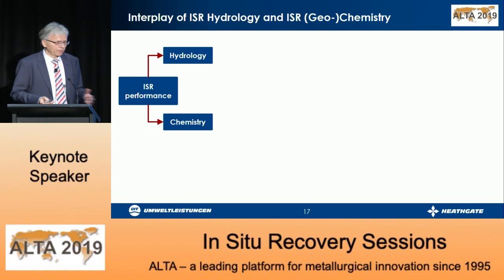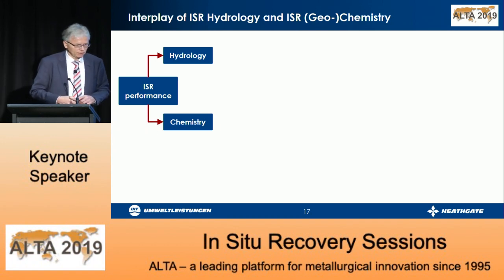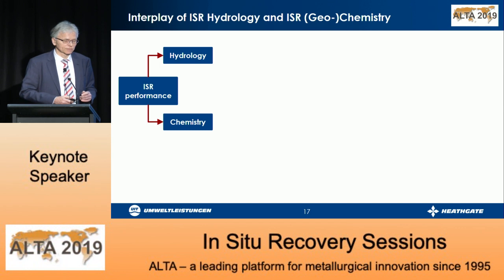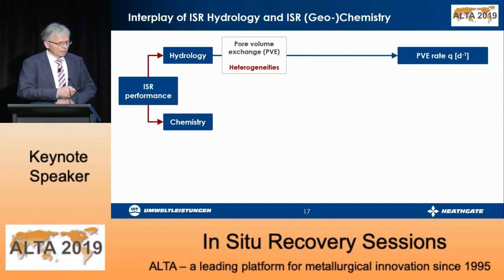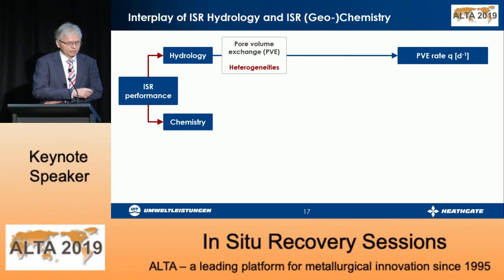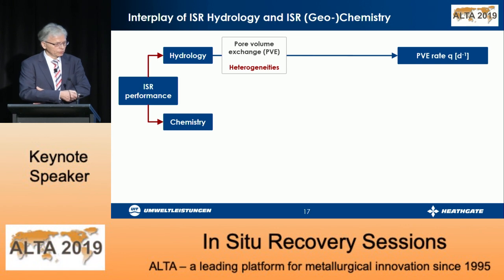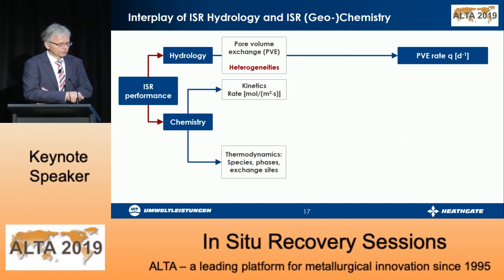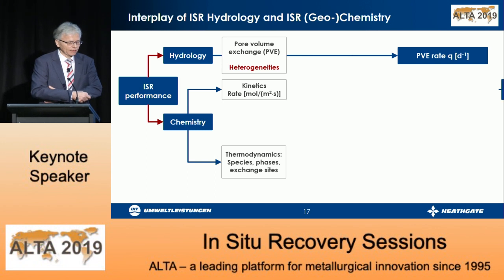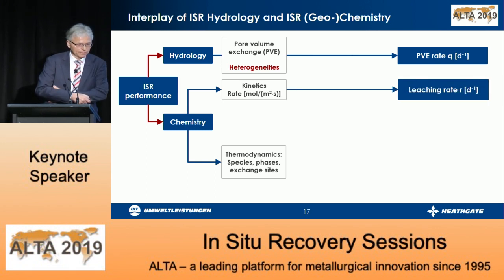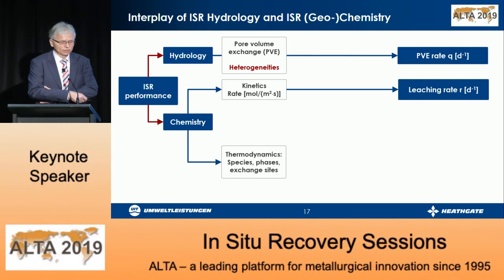Next point is the interplay of the ISR hydrology and the geochemistry, the two major sides of in situ recovery. Hydrological conditions are mainly defined by the pore volume exchange rate. This is nothing but the ratio of the volumetric flow rate over the effective porosity pore volume. Then the chemistry with the two sides, kinetics and the thermodynamic conditions. And with regard to kinetics, it's important to have an understanding of the leaching rate.